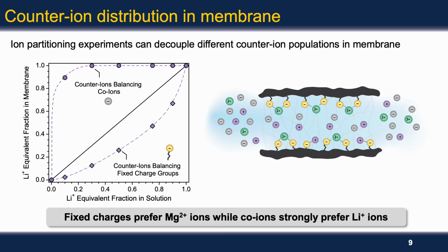To investigate this partitioning effect, we performed ion partitioning experiments that can decouple the different counterion populations in the membrane. The key results are shown in the plot here, which shows the lithium equivalent fraction in the membrane versus the lithium equivalent fraction in solution alongside the parity line.